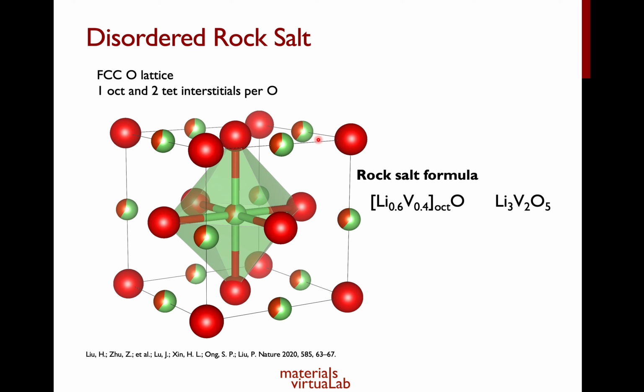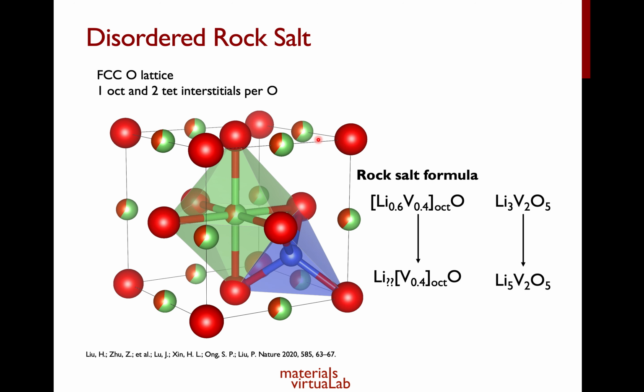Now, in Li3V2O5, you have 60% occupancy of lithium in the octahedral site and 40% occupancy of vanadium in the octahedral site, right? Now, this is the starting point of our disordered rock salt. When you lithiate, the obvious thing is that since all the octahedral sites are occupied, there are no other octahedral sites to occupy. Naturally, your lithium has to go into the tetrahedral sites, right? So I have deliberately colored this tetrahedral lithium a different color just to distinguish it from our octahedral lithium sites.